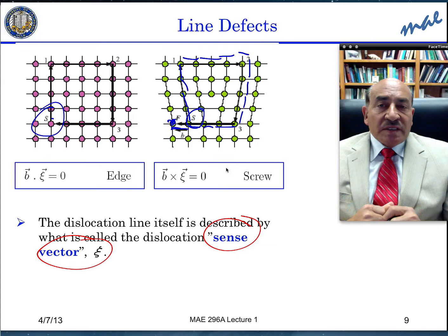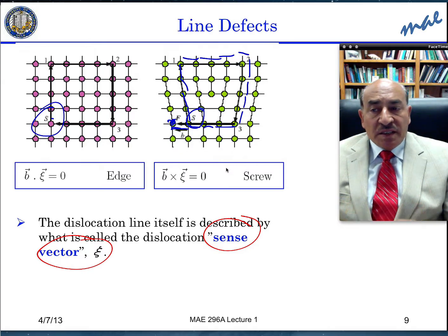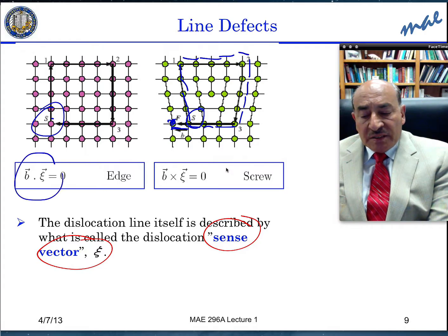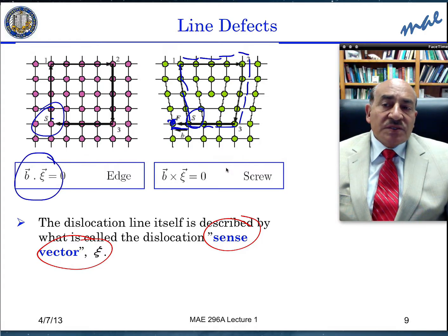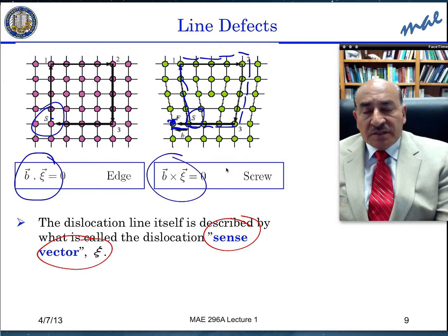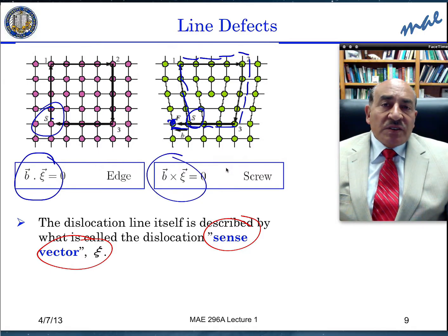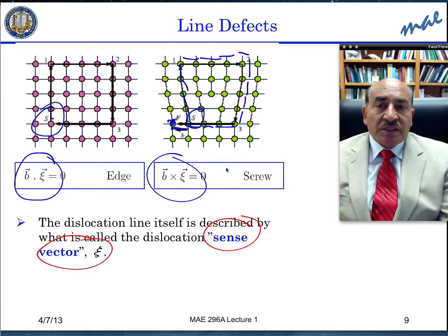And since the Burger's vector is perpendicular to the tangent line xi, we have the simple mathematical condition that the dot product of B and xi must equal 0 if it is an edge dislocation, and the cross product of B and xi must equal 0 if it is a screw type dislocation.